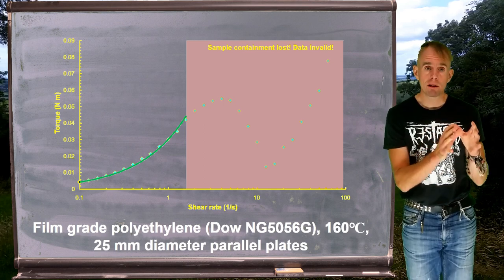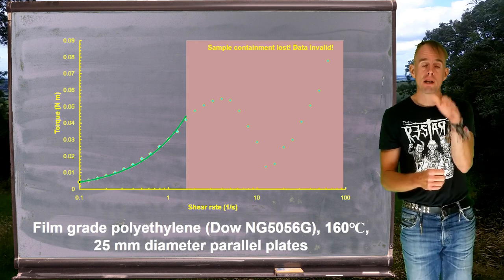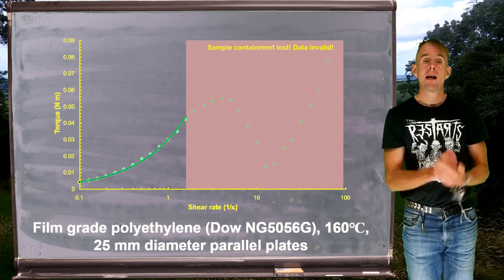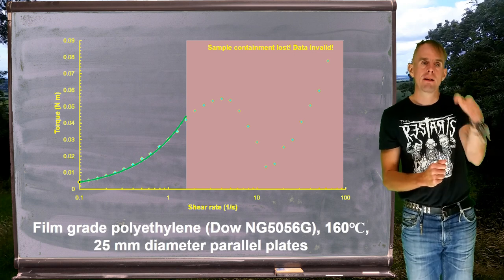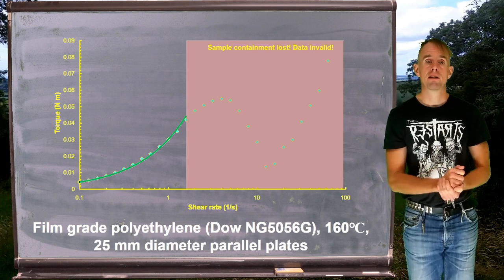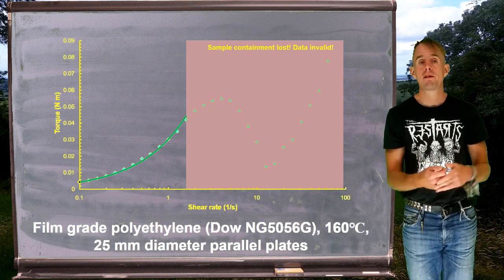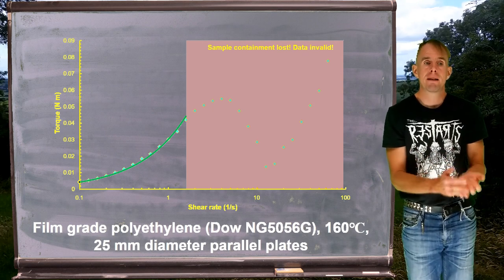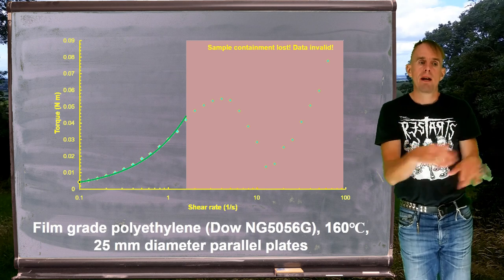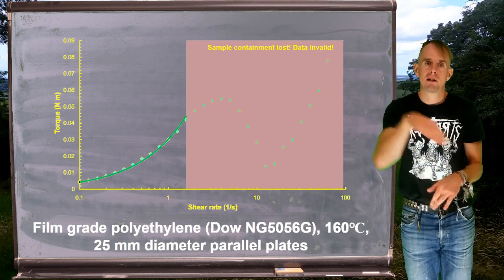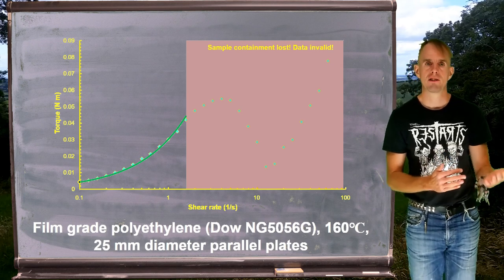We discard all data above 2 s⁻¹, leaving a valid shear rate range of about 0.1 to just above 1 s⁻¹. To the valid torque data, I fit an analytical best-fit curve, because I need to differentiate torque as a function of shear rate. Rather than numerically differentiating the experimental data — which introduces variation — an accurate analytical expression can simply be differentiated analytically.